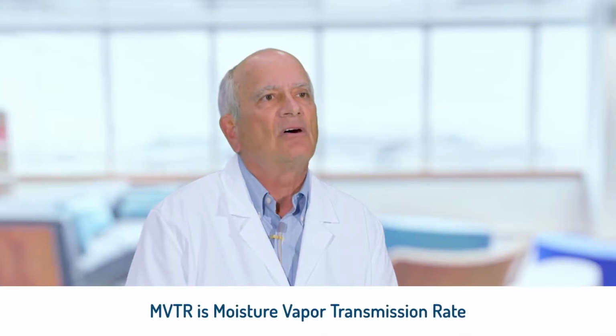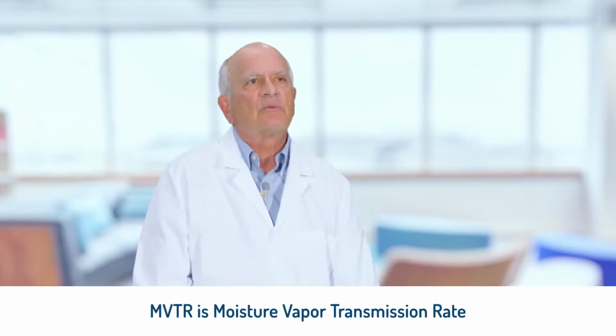The breathable dressings benefit from a high measured moisture vapor transmission rate value, or MVTR. This is a measurement of breathability, and it's unsurpassed by any other product on the market. But when it's time for removal, the polymer can be turned off. The adhesive bond drops off with a small swipe of rubbing alcohol, or isopropyl alcohol, around the border of the dressing, bandage, or tape.